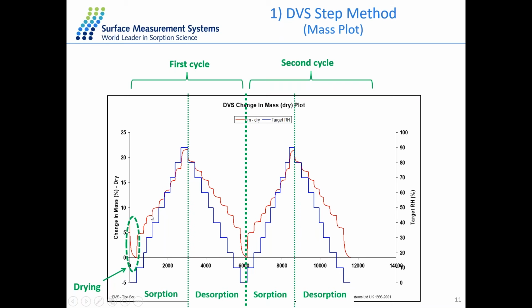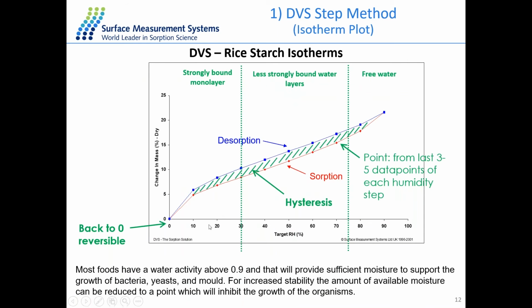And if you take the change of mass at the end of each humidity stage and plot it against the relative humidity, then you will get this isotherm plot with both sorption and desorption branches, with target relative humidity and change of mass.